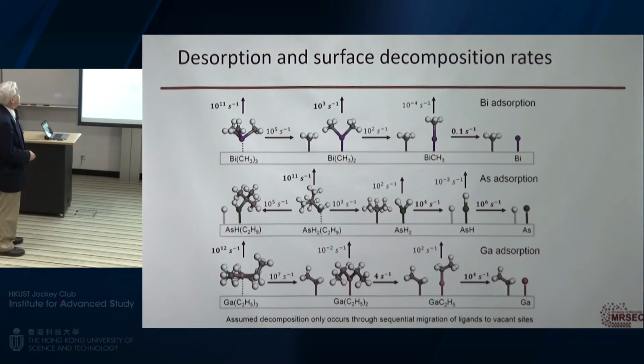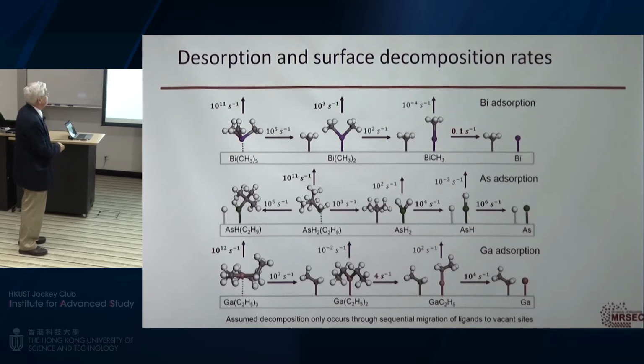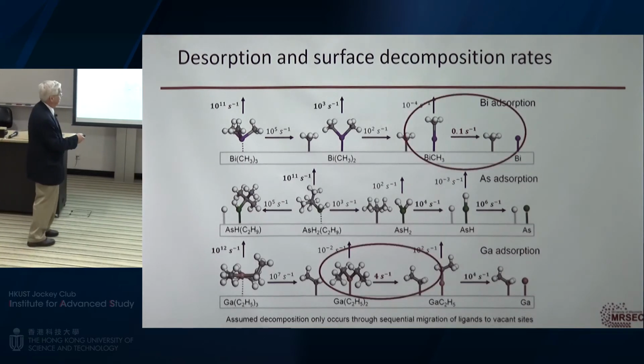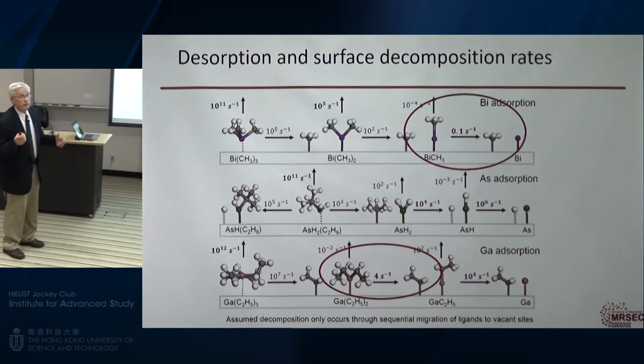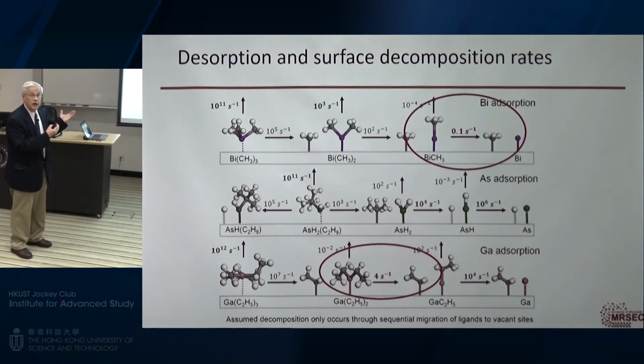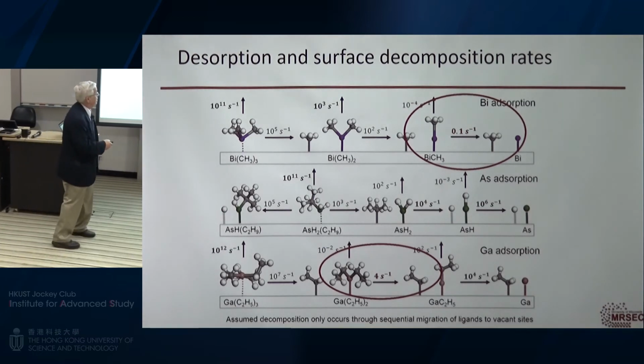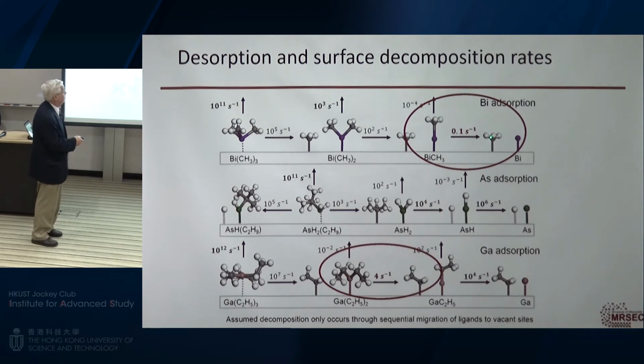And so we went through and we calculated all these reactions, and these are the rate constants associated with bismuth, gallium, and arsenic for all the various basic reactions. And what you find is that the slowest one was basically removing the methyl group from the bismuth atom. So the rate limiting step was removing methyl groups. So the way we've stabilized the surface is by adsorbing a chemical species on it that prevented surface diffusion and phase separation.